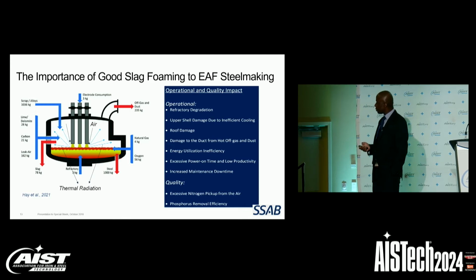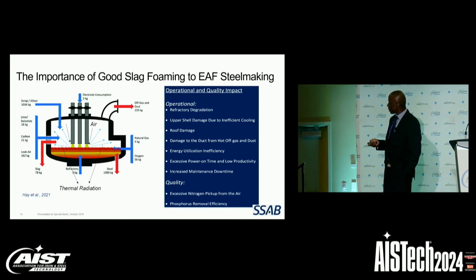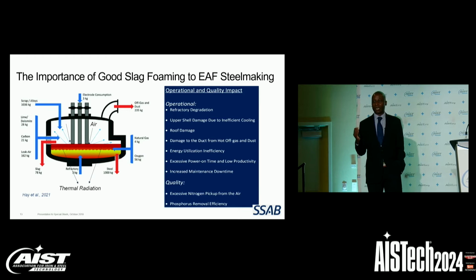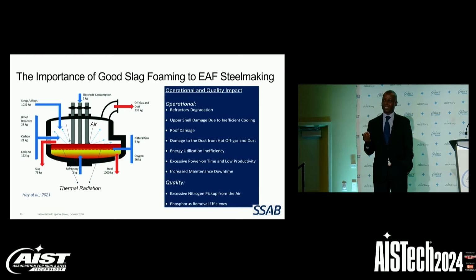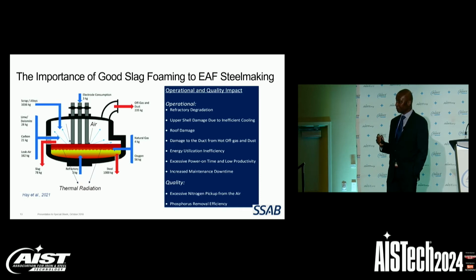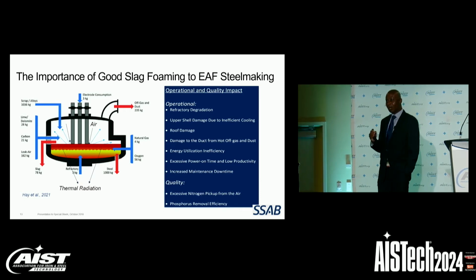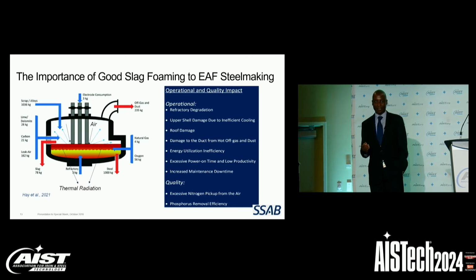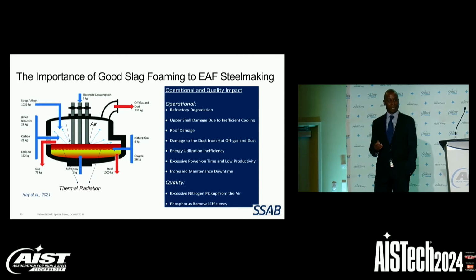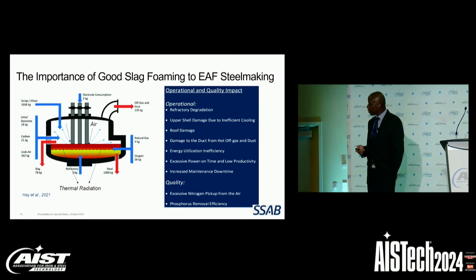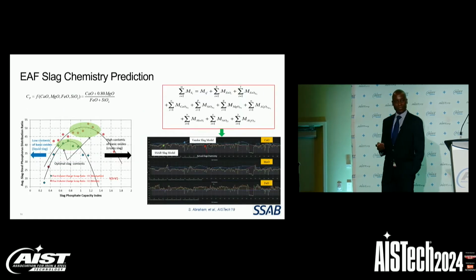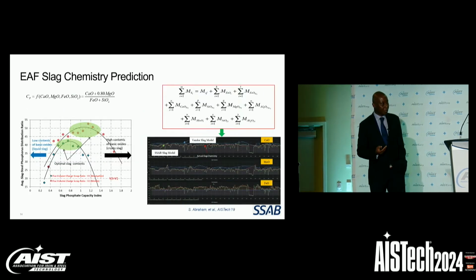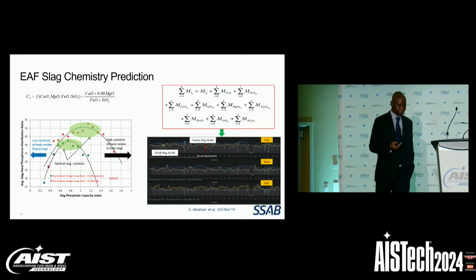Now, if the slag does foam well, then the slag completely engulfs the arc, maximizing heat transfer onto the scrap. And also, this process minimizes nitrogen dissolution from the air into the steel, which is good for the quality of the steel. But operators do not know exactly what the chemical composition of the slag is during the scrap melting. So to provide a solution to this, we decided to develop a model for predicting slag chemistry.